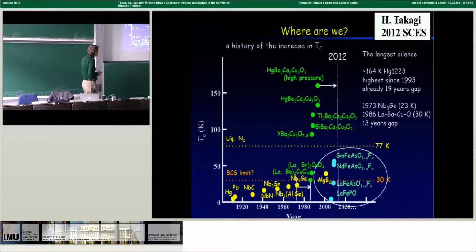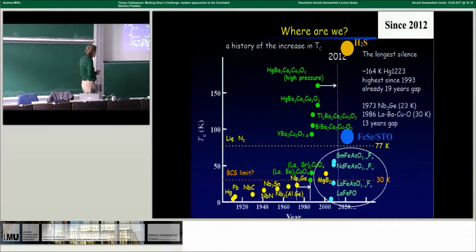summarize, here is a plot, which I also showed yesterday, of superconductors known as of 2012 and their transition temperatures, color-coded for different families. Here are 2 more examples discovered serendipitously. H2S, hydrogen sulfide, probably under pressure, with probably the highest known transition temperature of a material, and a monolayer of iron selenide on strontium titanate. Right? Each of these things was discovered by accident. These 2 were the result of optimization of known properties. People essentially reasoned by analogy based on what we had, and using that analogous reasoning were led to these compounds.